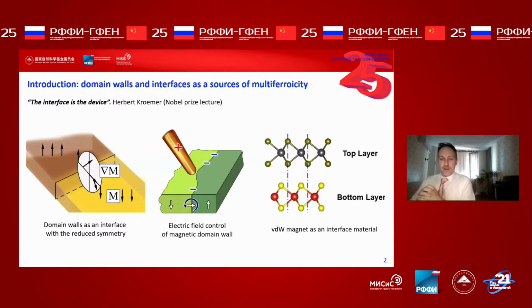The main idea of our project is in interfaces. Interfaces can be a special phase of the material that have properties different from the bulk material. For example, a magnetic domain wall, that is the interface between two homogeneously magnetized domains, locally reduces the symmetry of the material and can be electrically polarized. In this way, it can be controlled by electrodes.